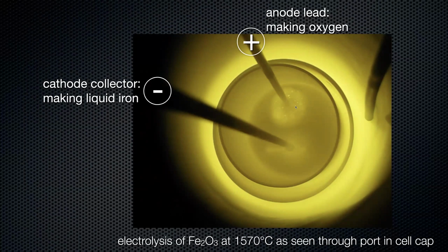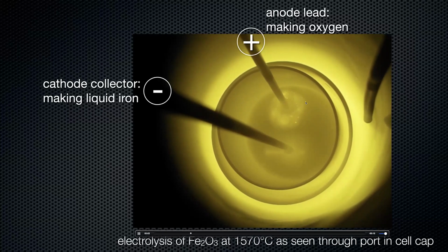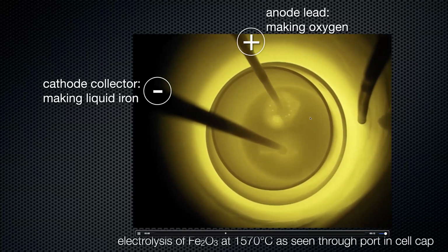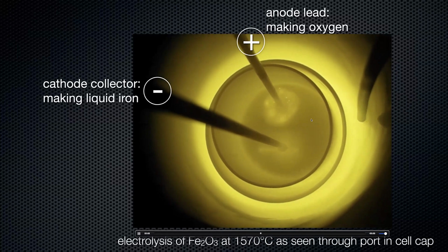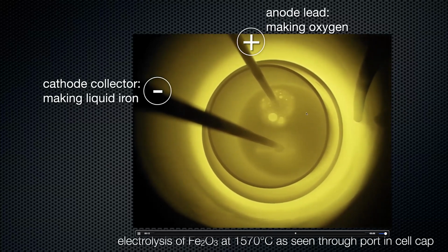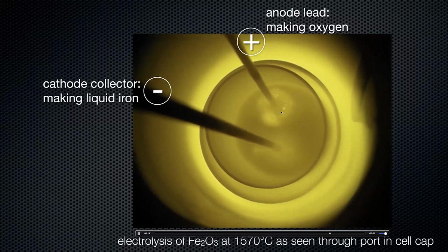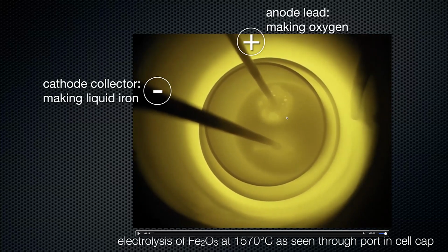You will see oxygen bubbles forming on this anode over here. And this other electrode, that's a molybdenum plate, and it's vertically disposed. Maybe you can see the very faint outline of the top of the molybdenum plate. So liquid iron is forming on the surface of that plate and falling to the bottom. So it's a silicate melt. It's iron oxide dissolved in silica, alumina, magnesia. And so it's viscous, but it still allows for adequate mass transfer. You can see bubbles coming off and so on.